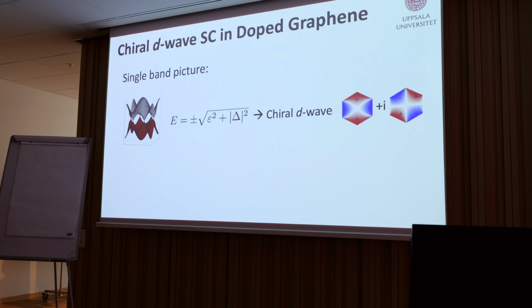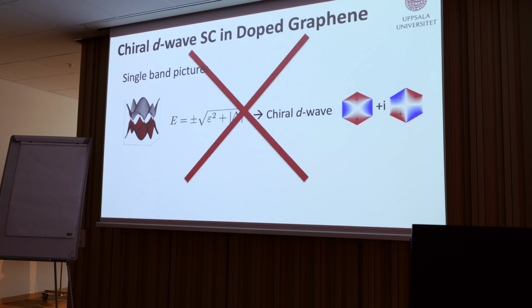It doesn't mean the chiral D-wave cannot happen, but it means it's not naturally favored over all the other D-wave states. So this is, to me, the biggest difference between the twisted bilayer and the monolayer, within the assumptions I'm making, that you have such strong interband pairing, and it's always there.